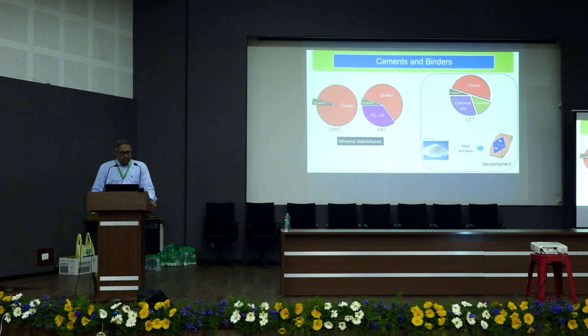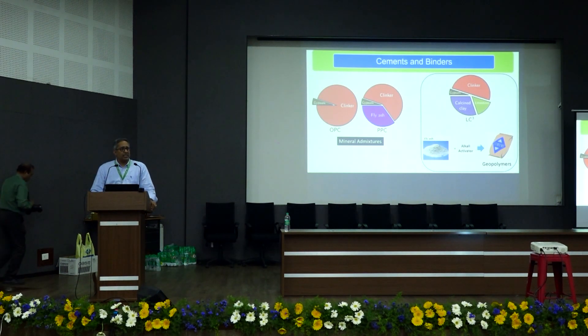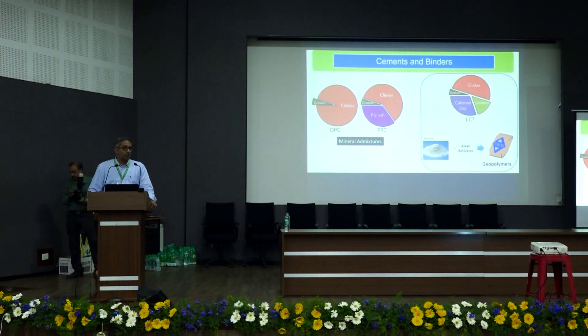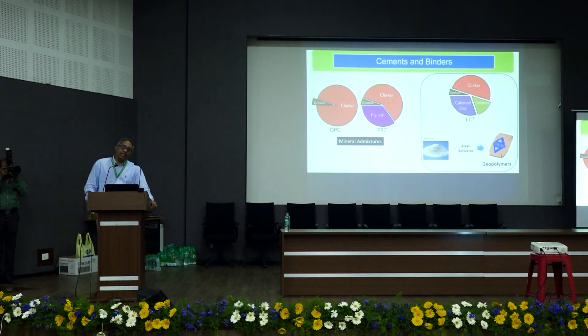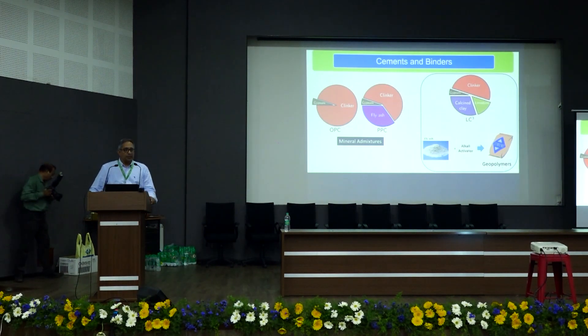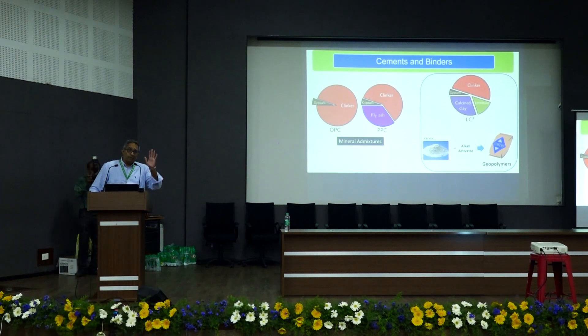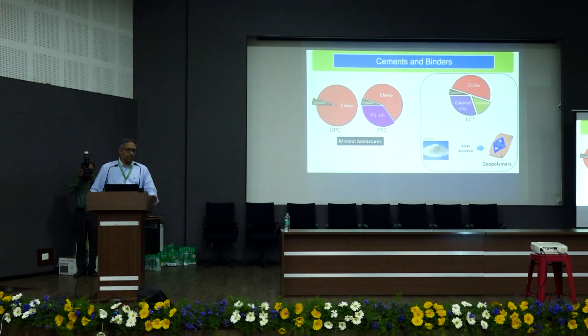India has seriously started looking at reducing clinker factor more than any other country. Today we find cements with clinker factors of 50% being allowed by the code for structural use. That has been possible because we have consistently done research on fly ash and slag, and we are able to produce PPC and PSC commercially — something that does not happen in Europe or the US.